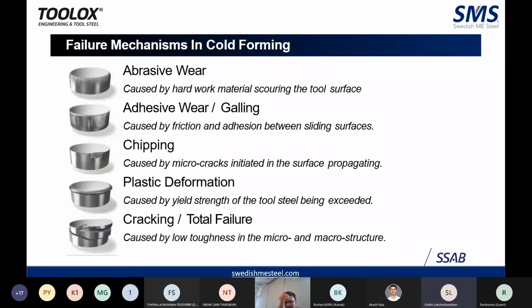So when you look at cold forming, there are different failure mechanisms associated with it. One is abrasive wear, which is caused by hard work metal scoring the tool surface. Adhesive wear happens due to the friction and adhesion between the sliding surfaces. Chipping is considered a major problem. It is caused by micro cracks, and the micro cracks, once initiated, will propagate through to the surface. Plastic deformation is also a major failure mechanism that you face, and also cracking. Particularly with cracking, since Toolox comes with high toughness, that helps you in addressing the problems faced with cracking. Then Toolox can be an effective and efficient material in replacing or addressing those failure mechanisms.